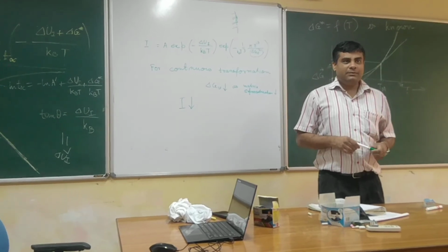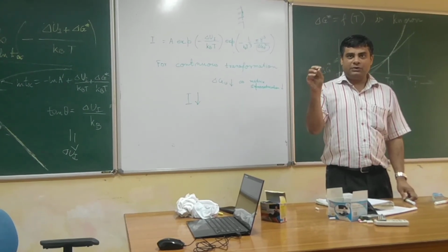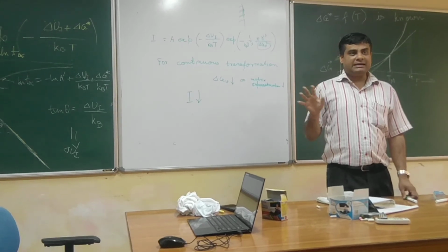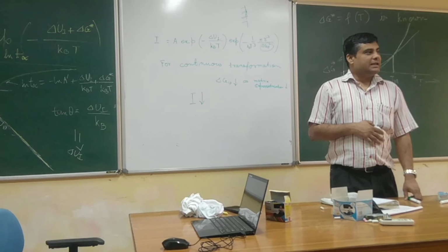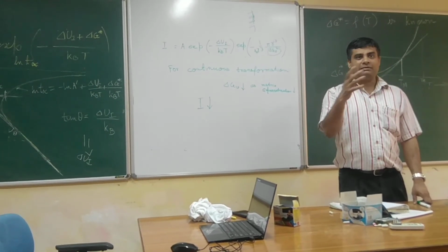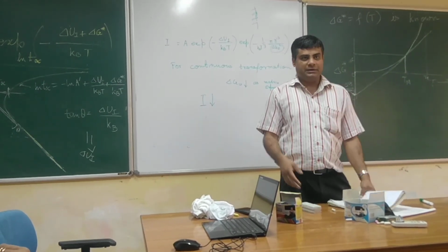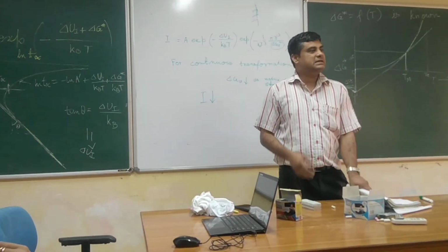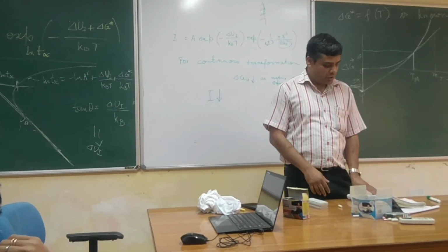So that's why you will see, if you see the nucleation of cementite out of ferrite, then it quickly goes to steady state, and then there is no nucleation, no further nucleation. Whereas if it is eutectoid type of product, the nucleation keeps on going.